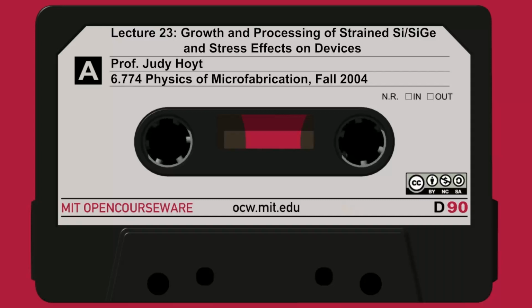If you make an alloy anywhere in between and you have it thick enough that it relaxes, you can use a linear interpolation. It's not quite perfect, but you can use a linear interpolation. So at 50% silicon germanium, or 50% germanium, the lattice mismatch is about 2%. So there are 2 different types of silicon germanium that people tend to talk about. One is when you start with a silicon substrate and you grow a very thin layer, say a few hundred angstroms, of silicon germanium on silicon.